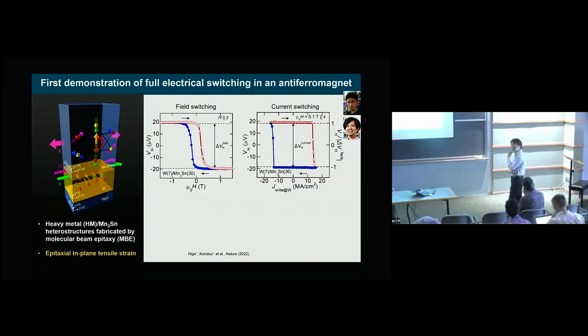That's very interesting. Yeah, if you want to design a magnetic texture, we need to know that. This material has been known since the 1970s, and there has been neutron diffraction measurement. Nagamiya-sensei, the theorist for antiferromagnetism, found that the Dzyaloshinskii-Moriya interaction along the z-axis is very strong and has a negative sign, which makes the spins antichiral. But the question is where this sign comes from, right? That part, I do not really have a very good answer for.